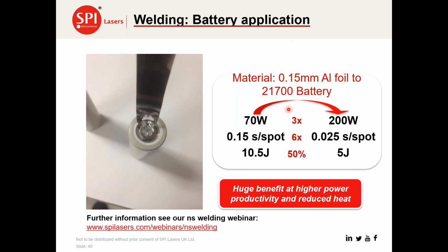What's been interesting is that we've managed to move forwards in terms of available power. So when we started the welding process, we started with 70 watts. And for welding these very thin foils, like the 150 micron aluminium foil to one of these battery cells, we don't really need much pulse energy, and we can create a spot in a fraction of a second. What's been interesting is that with the higher power, we can benefit from the heat accumulation from welding quicker, which means that we can weld 6 times faster for a 3 times increase in weld or average power, which equates to a halving of the heat input into each of these particular spot welds.